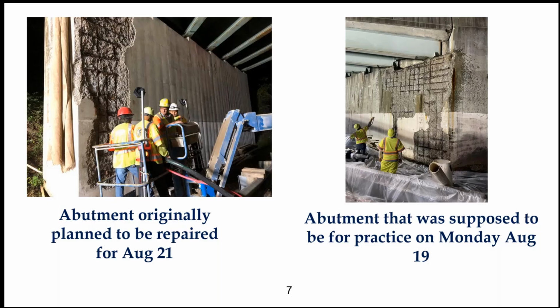So here are pictures of the application, where you have a man lift with the equipment ready for the application. Originally we had one side as a trial test, and the other side was supposed to be the actual repair, but we ended up switching around due to the traffic control. The quantity of material, because the material was brought from FIU on a truck, was not enough to do the entire repair. However, it was good enough to show that the repair actually works, and that spray applied UHPC is a good technology that will provide the protection needed, as well as the restoration of the bridge to serviceable condition. At this point, next slide, please.